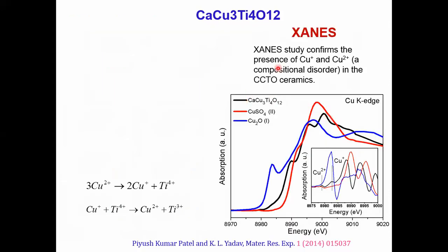So here also we did the XANES studies, confirming copper and copper. This was calcium copper titanate material. So there is a copper+ and copper2+ transition, a compositional disorder in the CCTO ceramics, which is causing this very high dielectric value.